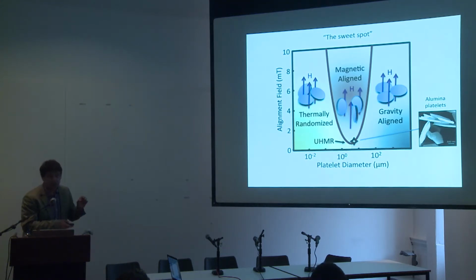But what was really a surprise to us was how low the magnetic fields needed for such an effect were. We typically use tens of millitesla. Just to give you a feeling for it, this is the kind of magnetic field you get from the magnetic stripe of your credit card. Very, very low fields. And we went on to study this, and we realized that we're actually in a sweet spot in terms of particle size.